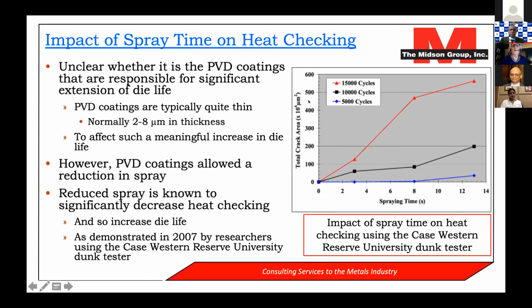So what this figure shows on the y-axis is the amount of heat checking. 600 is lots of heat checking, 0 is obviously no heat checking. And then on the bottom is spray time, and the three different lines are 5,000, 10,000, and 15,000 dunks. So if we look at the maximum spray time, 13 seconds, you can see after 15,000 dunks, we are seeing a lot of heat checking. If we take that spray time down from 13 to 3 seconds, much less heat checking.